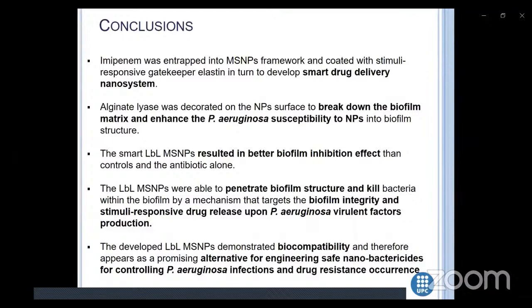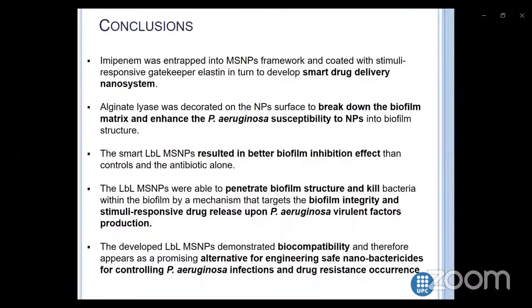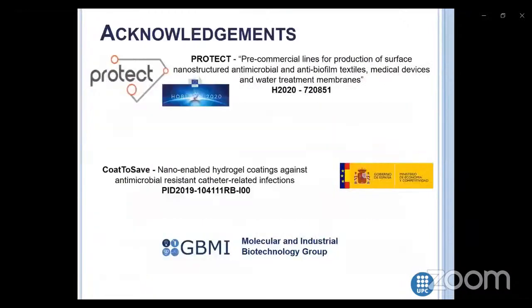These layer-by-layer nanoparticles resulted in better biofilm inhibition effect compared to the controls in the bulk solution of the antibiotic. The layer-by-layer mesoporous silica nanoparticles were able to penetrate the biofilm structure and kill the bacteria in already established biofilms. So the developed layer-by-layer mesoporous silica nanoparticles demonstrated biocompatibility and could be promising alternative for nanobactericides for controlling bacterial infections and drug resistance occurrence.